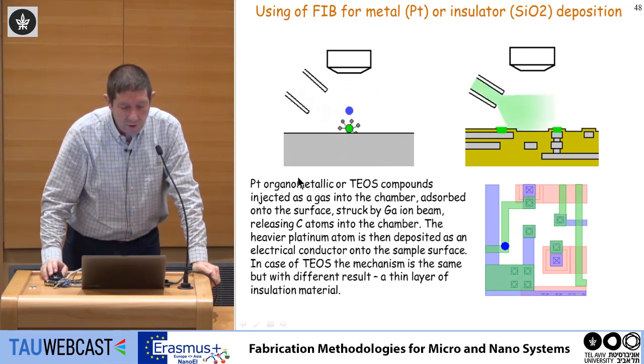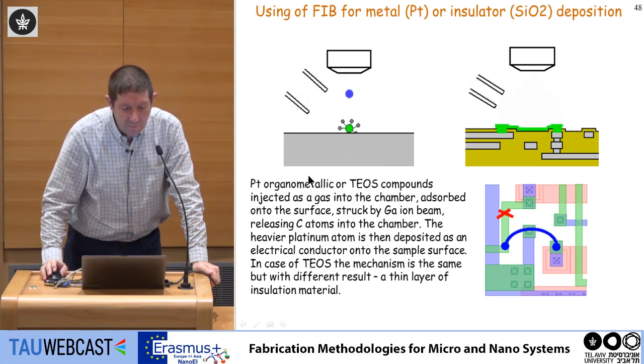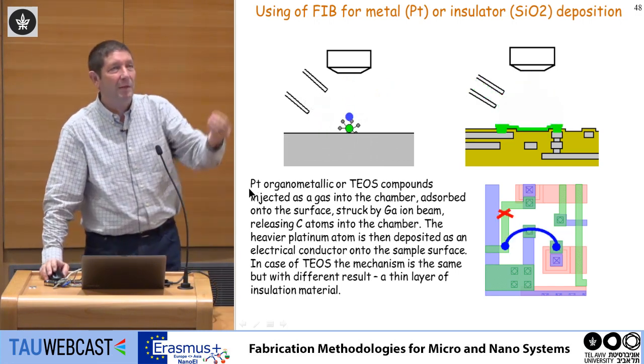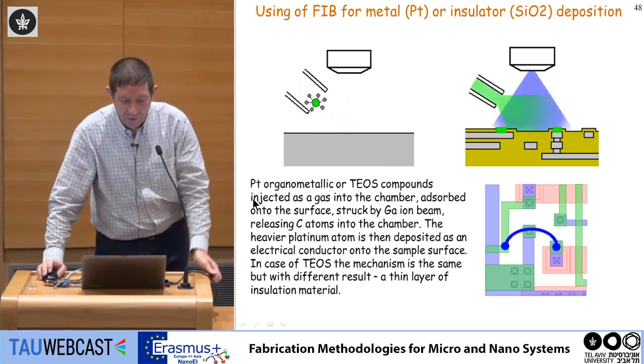And you can use platinum organometallic or tetraethyl orthosilicate compounds injected as a gas. Some platinum organometallics or tetraethyl orthosilicates are gases, and you eject them from here. They are adsorbed to the surface, and then the gallium hits them and breaks the organometallic compound and leaves a platinum residue or a silicon residue.